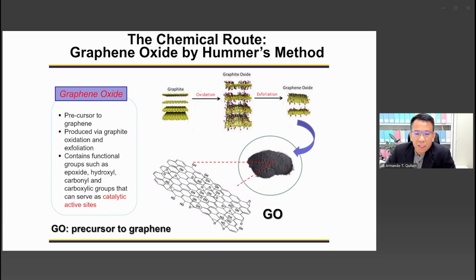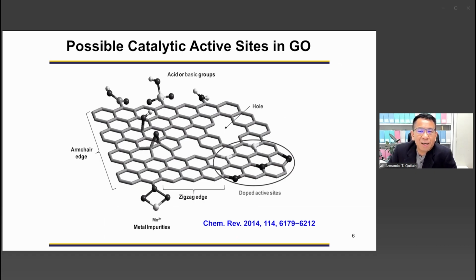And this is the structure, all right, of graphene oxide. You have those oxygen functionalities on the surface of graphene oxide. This is not graphene. This is graphene oxide with those oxygen functionalities. If you would like to obtain graphene, you need to remove those oxygen functionalities. All right. So these are some of the possible active sites in graphene oxide, which you can use as catalyst, like, for example, acidic or basic groups. It also has carboxylic groups, the COOH, and a very unstable epoxide, right? So the epoxide forms OH groups and H+ instantly in water when you dissolve this in water.